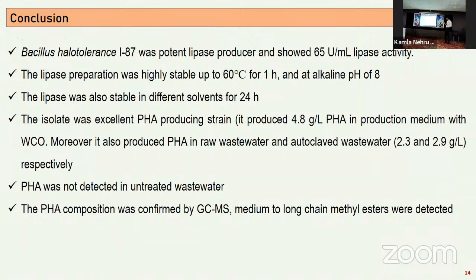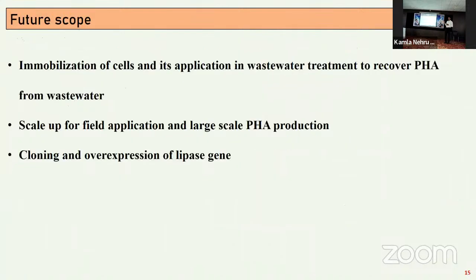So in conclusion, we saw that we got a very good strain which had good lipase activity as well as good lipase stability, and it produced very high PHA, 4.8 gram per liter in PHA medium, and in wastewater up to 2.9 gram, which is very high because in literature, in wastewater, the values range from say 0.5 onward. So yield was good in that sense, and of course we can further optimize it. PHA was not detected in untreated wastewater where we did not add our inoculum under the same conditions. So the presence of this culture is very important. It really played the role.